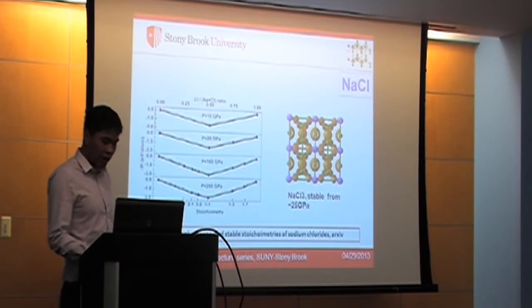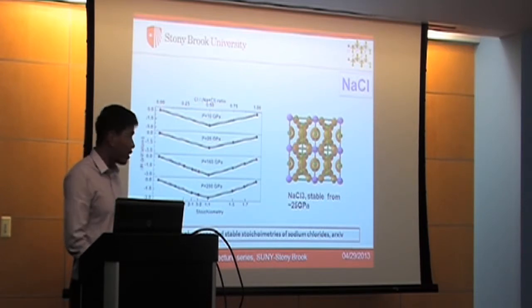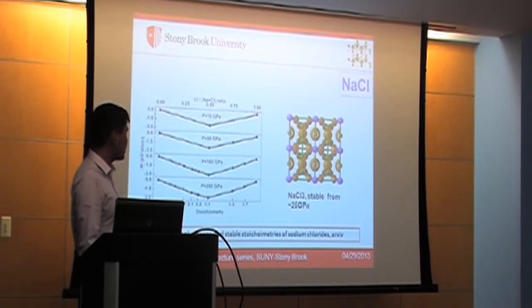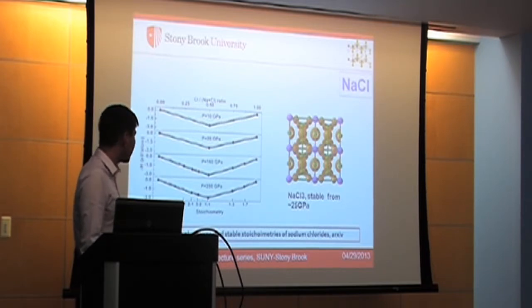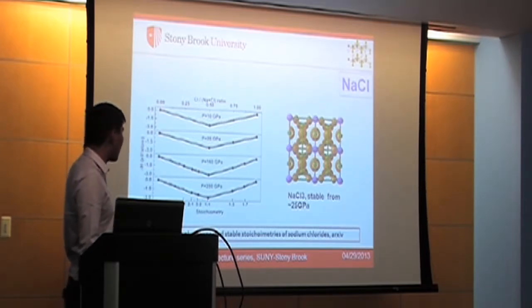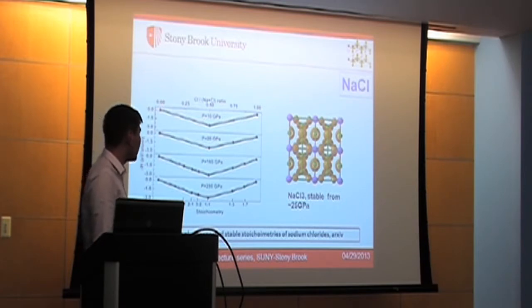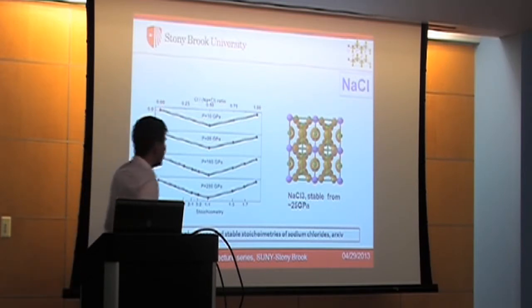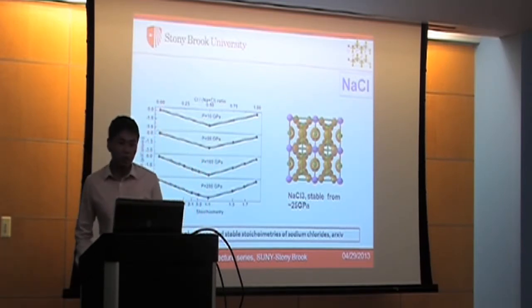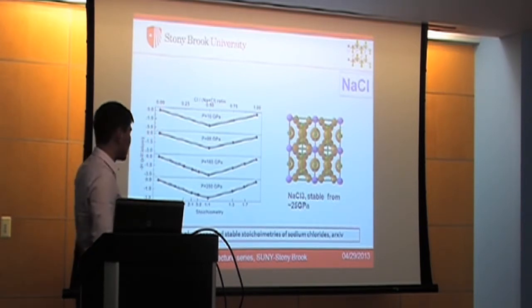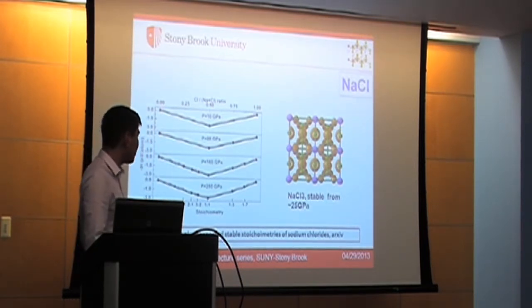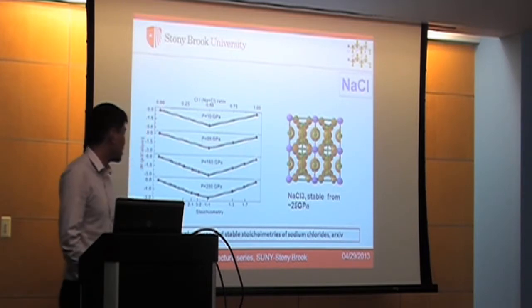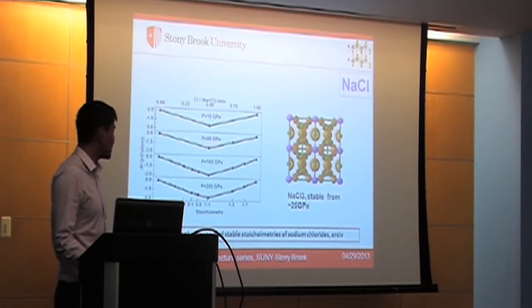So when we increase pressure further, we found that actually for this system, it can have many different stoichiometries, from the sodium-rich boundary to the chlorine-rich boundary. For instance, for this particular system, 1 to 7. If we don't know any knowledge about this, can we expect such kind of exotic compounds? Can NaCl7 exist at pressure? The calculation shows yes, it can.